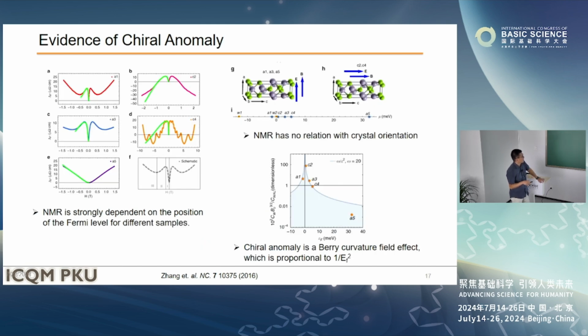firstly, we found that this negative magnetoresistance is not dependent on the crystal orientation. It can exist in any direction, like the a-axis and the c-axis. Also, we grew different batches of samples, because of the chemical vapor transport method and the low carrier concentration. We found that different samples may have different chemical potential, the Fermi energy. And we measured those samples, and found that some compounds show a negative magnetoresistance, and some don't, meaning it is strongly dependent on the position of the Fermi level.